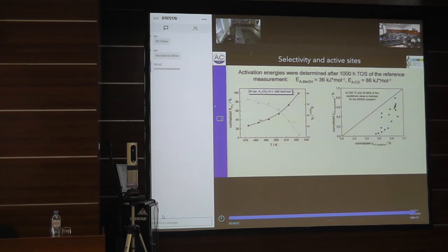And what you also see here is what I plotted: the normalized yield of CO in equilibrium and the normalized yield that we get experimentally. And if that would be the equilibrium, we should see a straight line. And you can see it's not a straight line. That means we run the methanol synthesis under full equilibrium conditions. The CO synthesis is not under full equilibrium. That means there is a kinetic barrier for reaching the reverse water gas shift equilibrium. And this kinetic barrier is to our advantage.